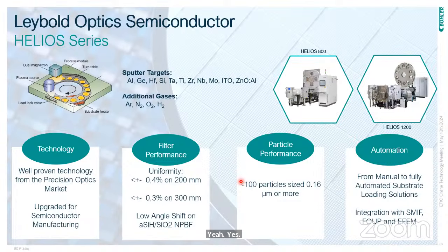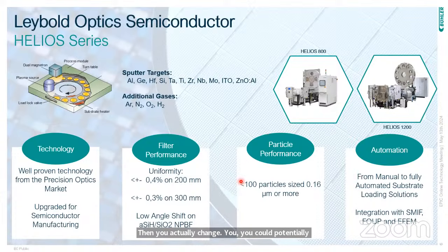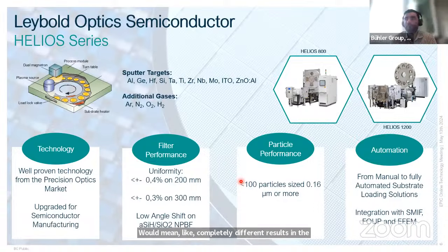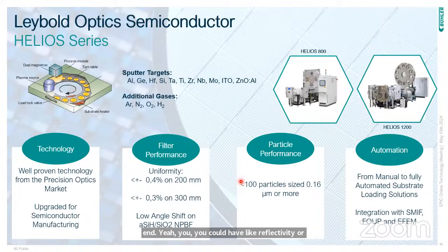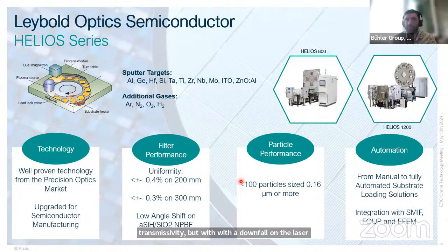And for example, if your automatic system is adjusting just to match the desired outcome, then you could potentially change the whole stack structure in order to achieve that design, and that could mean completely different results in the end for a laser optic. Yeah, you could have reflectivity or transmissivity, but with a downfall on the laser damage, which will affect this.